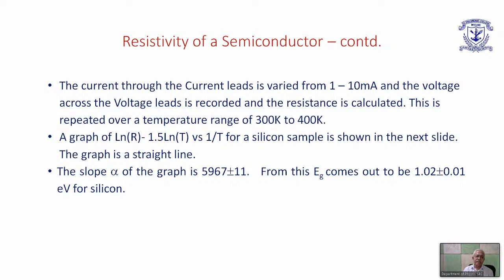We can calculate the slope of the graph. For the sample for which the data is presented, the slope is something like 5967 plus or minus some 11. And Eg, as we noted earlier, can be calculated knowing the slope, and its value turns out to be about 1.02 plus or minus 0.01 electron volt for silicon. As you all know, for silicon, the band gap is something like 1.1. So this is quite close to the value.